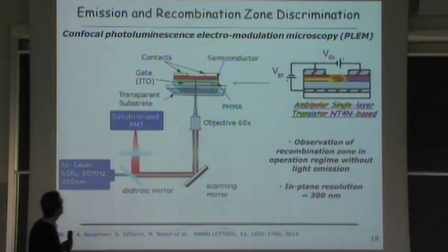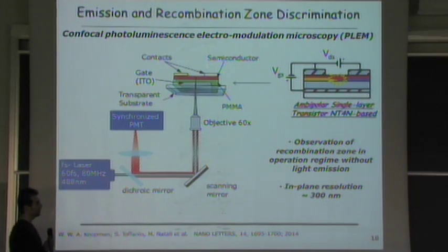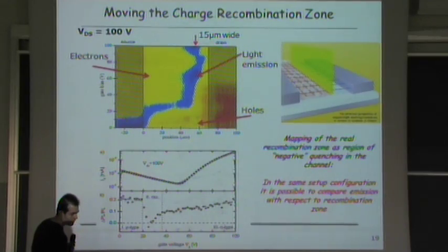So for that, we implemented a new characterization tool. It is named confocal photoluminescence electromodulation microscopy. And it is very useful because we can observe the recombination zone in operating regime without light emission. The in-plane resolution is more or less 300 nanometers, so we can apply this technique to different devices.